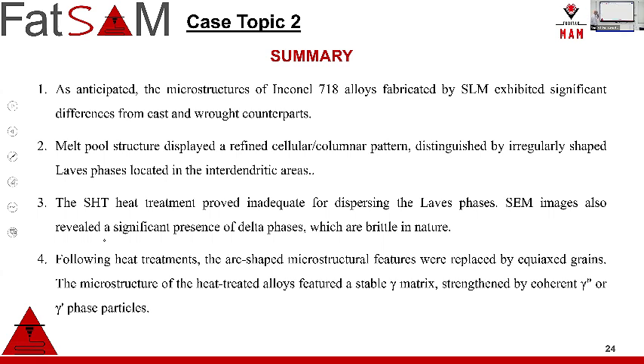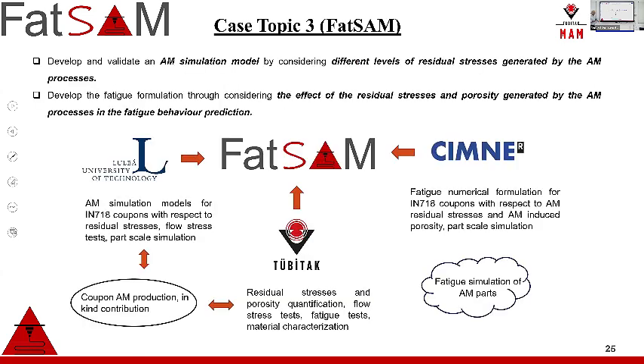So, final summary: with heat treatments, the arc-shaped microstructure features were replaced by equiaxed grains. This is one of the biggest successes of this post-processing study. And we have a stable gamma matrix strengthened by gamma double prime or gamma prime phases, which we can easily see from the grid results. And finally, FATSAM.